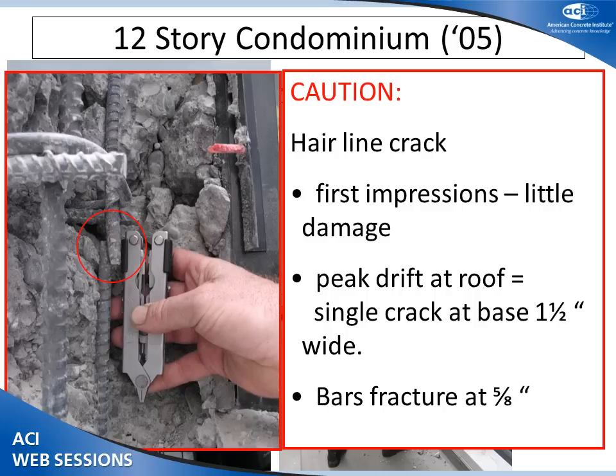And the Aussie team came through and they hacked out all the bars along that wall and another wall and found that every single longitudinal bar in that 11-storey wall was fractured at one crack. And I know of 3 other buildings that we had a look at that had exactly the same problem. There simply isn't enough longitudinal steel to form a distributed zone of plasticity. What we found was that first impressions were that the cracks meant there's no damage. I believe there's a recommendation in FEMA that if a crack in the wall is less than 5 mils, just epoxy it up. I'm not so sure that that's a good tactic to take at the moment. We have another way of dealing with this, which I'll talk about in a moment.